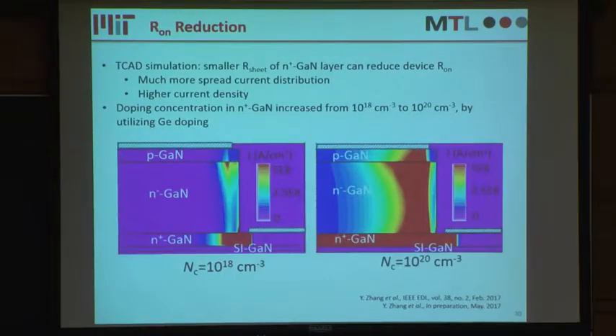After optimizing the reverse characteristics, we also wanted to optimize the forward characteristics. We did extensive TCAD simulation, and found the sheet resistance of this N+ gallium nitride current spreading layer is key to reducing the total device on-resistance.